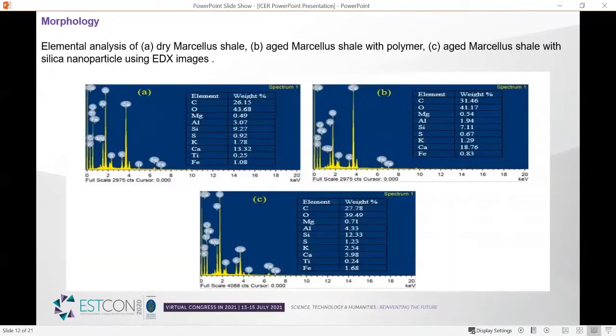So also we have conducted a morphology study using the EDX images to look into the morphology in the dry Marcellus sample, aged Marcellus shale, which was aged with the polymer, and also aged Marcellus sample with the silica nanoparticle. And we can see that the polymer adsorption happened in the aged sample B from the carbon increase, and less adsorption taken place in the sample C as the carbon decreased and the silica amount increased.